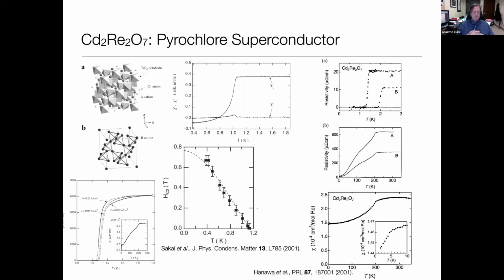the early 2000s, when cadmium rhenium oxide, which has the same pyrochlore structure I was mentioning before, was found to become superconducting. You can see the resistivity here shows a nice resistive transition at just above 1 Kelvin. You can see the Meissner effect in the expulsion of magnetic flux at the transition temperature. And you can measure things like the upper critical field, all good evidence of a bulk superconductor.